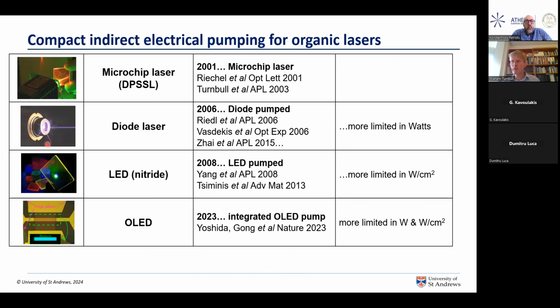So about 15 years ago, we did some initial work looking to see if we could use gallium nitride LED technology to pump the organic laser, and I'll show you a couple of our older results of that in a moment. This is quite a big challenge because it's difficult with a light emitting diode to get a very high power density, number of watts per square centimeter, into the organic semiconductor. And so it takes quite a lot of careful design physics and device physics to get that to work.